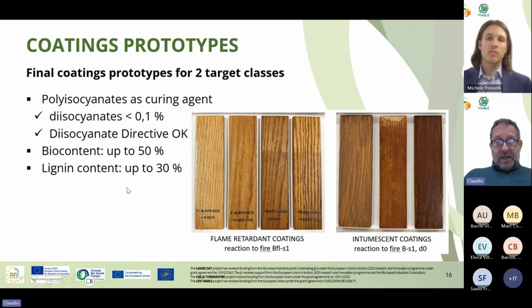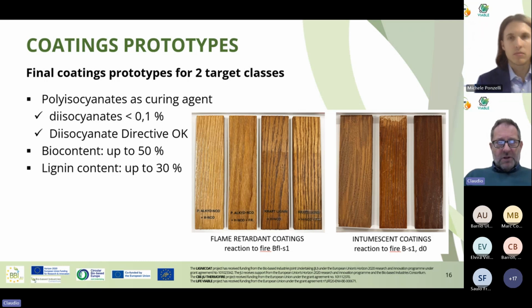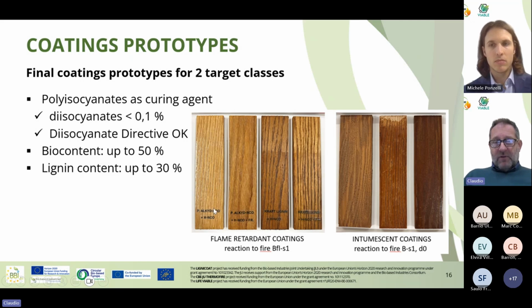The other numbers make us happy. We have reached a bio content of up to 50% due to the fact that we have used lignin, that is completely of bio origin, and we have also used polyisocyanates that are partly bio-based, and we have reached a lignin content in some of our materials of up to 30%. So again, this makes us very happy.